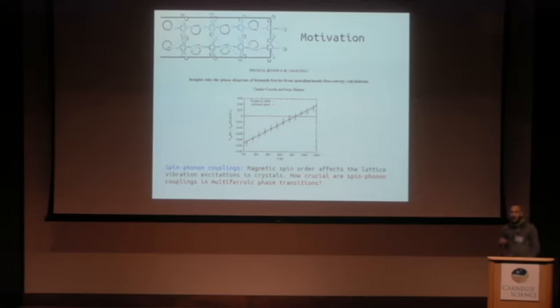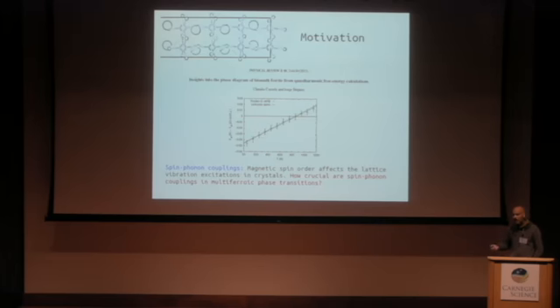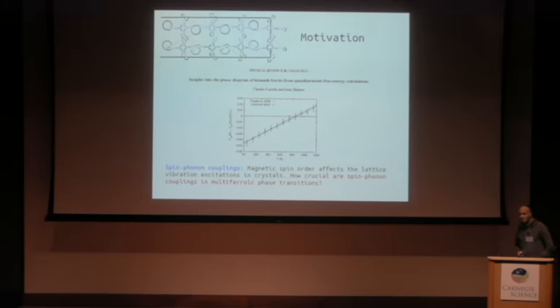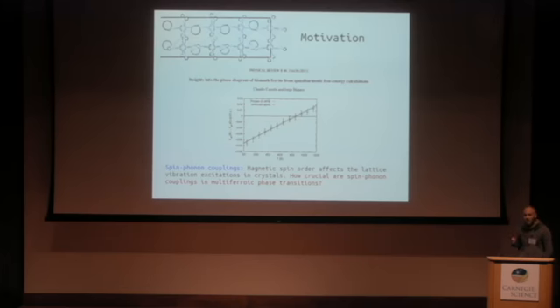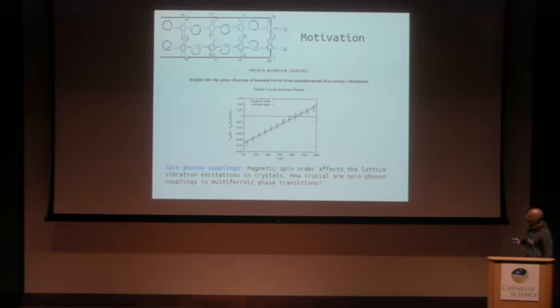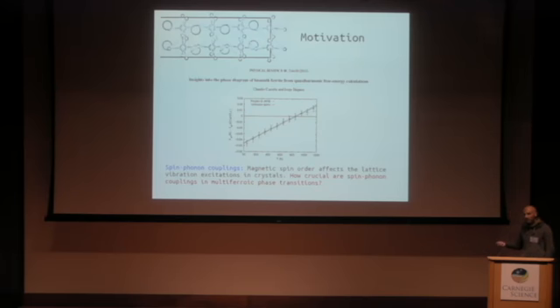We did that—this is what is called here 'unfrozen spins.' At the same time, we did a standard quasi-harmonic approximation constraining the magnetic moments to those seen in the ground state. For our surprise, we found out that it didn't matter too much, at least for the rhombohedral polar-to-paraelectric phase transition at normal ambient pressure conditions. When you heat up, at around 900 Kelvin you get the paraelectric phase, and the spin-phonon couplings didn't have any effect on that transition.